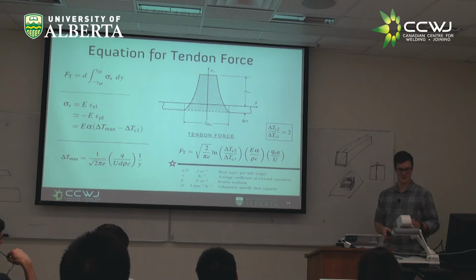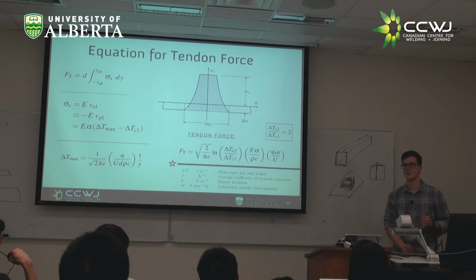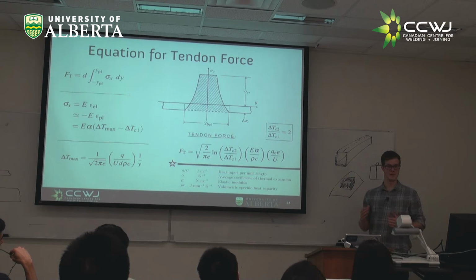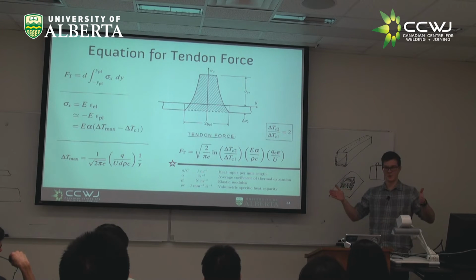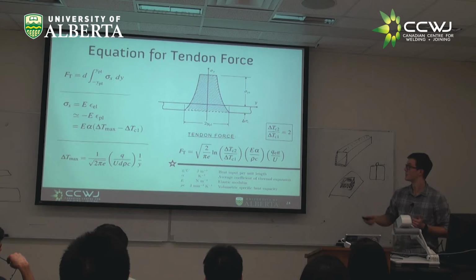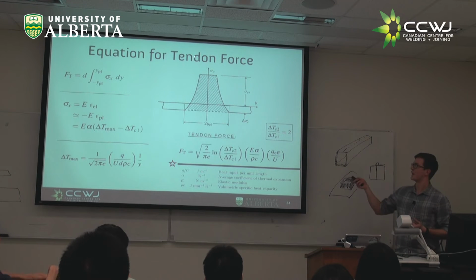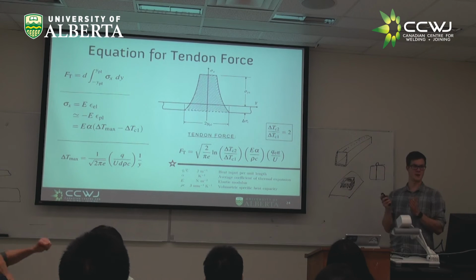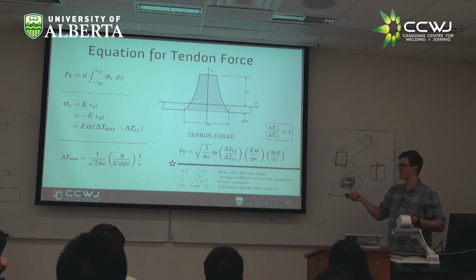So we talked about this a little bit. If you imagine that we're looking at those yield temperatures, if we have a higher strength steel, that yield temperature is going to be higher. The region of material we're dealing with, which is this width here, is going to be smaller. So we have higher stresses because yield strength is higher, but we have a smaller region. And what you see is that those two effects, when you actually go through and do the integration, the two effects cancel.